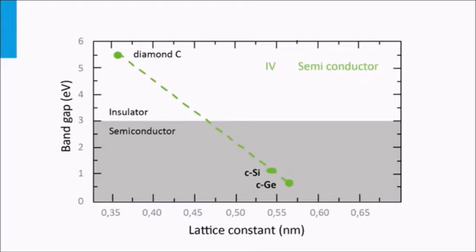Crystalline carbon is another name for diamond. We indeed see that the band gap is very large for diamond, as diamond has the smallest lattice constant. In a very simplified representation, a larger band gap can be considered as a larger overlap of the original sp3-like orbitals of the neighboring atoms. A larger overlap induces a larger splitting of the energy levels of the bonding and anti-bonding level.